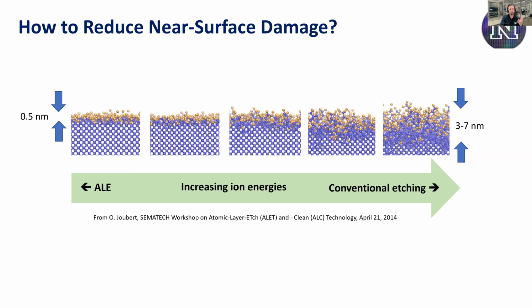Maybe I'm worried about surface roughness. Atomic layer etch, typically smooth surfaces. Awesome. In many cases, that's really, really important. However, what I tend to think of as the major advantage of atomic layer etch, and certainly why I'm very, very interested in it for quantum applications, is because of this reduced subsurface damage. So we're going to try to find a way to etch while putting less energy into our surfaces.